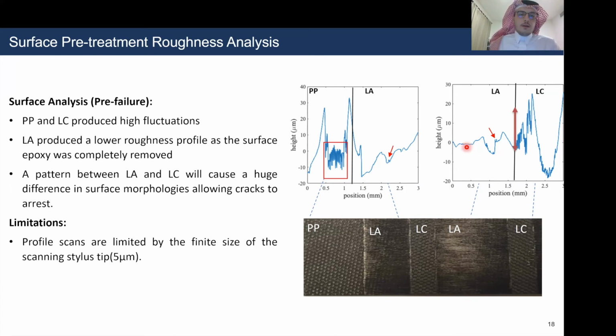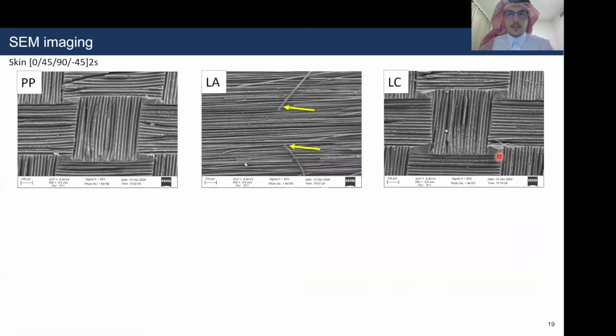A limitation of this scanning technique, or this topology analysis technique, is that the profile scans are limited by the finite size of the tip of the stylus. So as we know, the fibers of the carbon fiber can be 7 microns or even smaller, maybe 5 microns, and the distance between the fibers can be even smaller. So it might be difficult to get accurate scans, which can justify why there are some peaks appearing in the LA. Moving on to scanning electron microscopy imaging.